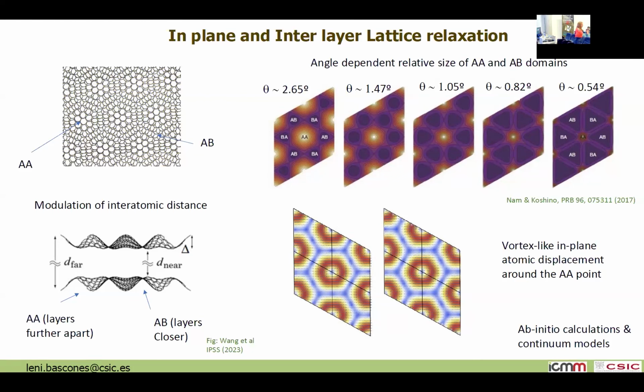That probably depends on each system, because Chern states have been observed in different systems. For example, for twisted bilayer graphene, you can have these Chern states even if you don't put this vorticity. One thing is the atomic vorticity, how the atoms move, and another one is just the electronic one. At the magic angle, the chirality also changes in the electrons, but you don't need to put the atomic vorticity to get these other Chern states. Normally what happens there is that you polarize it in terms of the valleys and things like that.